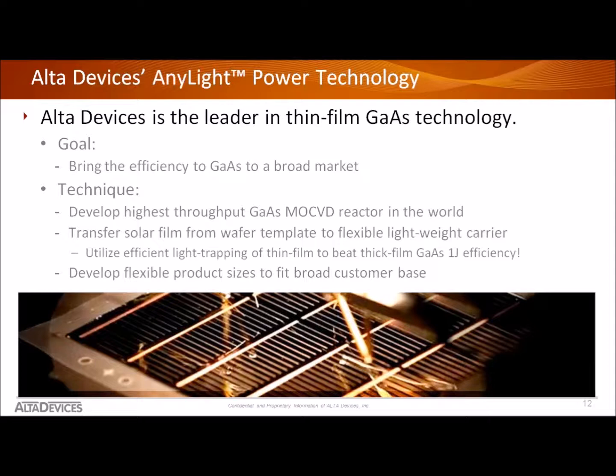One, we developed the highest throughput gallium arsenide MOCVD reactor in the world. Our reactor designs are patented. We work with industry leaders in tool development and can make material that is suitable for solar quality at a significantly faster rate than any other gallium arsenide reactor. We have to grow the reactor on these very expensive gallium arsenide wafers, but we transfer the solar film from the wafer template to a flexible lightweight carrier that's pictured below. And that way we reuse the wafer for growth.